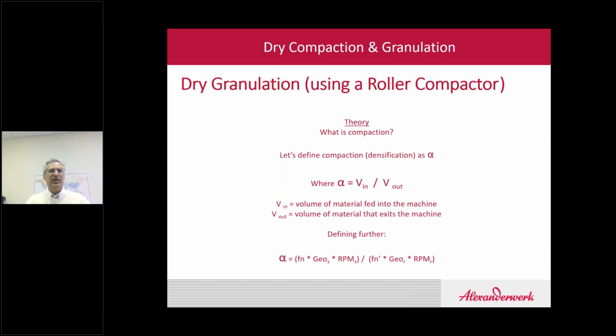So what are we actually doing in roller compaction? Dry granulation using a roller compactor really is changing the bulk density of the material. We're going to look at this a little bit closer, and let's get into the theory of it now by defining alpha. Let's call alpha the compaction or the densification, and that's going to be the volume in divided by the volume out. So the volume of the material fed into the machine divided by the volume out of the machine.